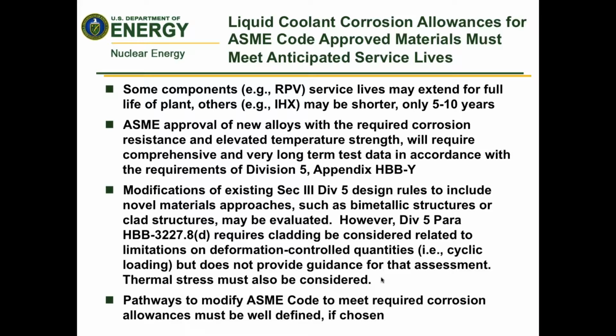On the other hand, if the decision is made that a recommendation is appropriate to use a coating or a cladding, first of all, one has to show that this is viable for the life of the component. Coatings have possibilities of being scratched, spalling, and otherwise creating holidays which would lose their protective ability. Cladding has a particular issue in as much as the code requires the use of or the consideration of deformation controlled quantities such as cyclic loading and thermal stresses, and there are simply no rules to do that. So that portion of the code would have to be developed.